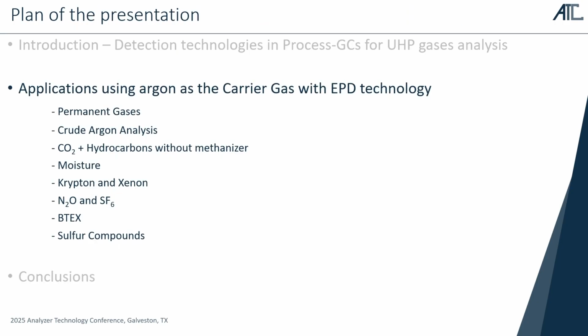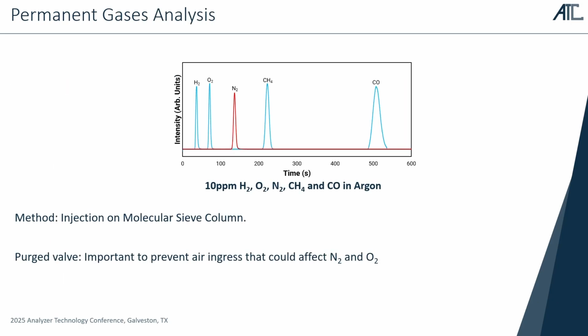So now for some applications that were developed with the EPD technology using argon as the carrier and discharge gas. The first example I would like to present is quite simple. It's actually the measurement of permanent gases in argon. So here you have a standard chromatogram that was acquired for a simple injection on a molecular sieve of 10 ppm permanent gases. But this result highlights the importance of the GC valve that was used, because if the valve is not leak tight, then you would definitely have some interference from air on the nitrogen and oxygen peak. So having a valve that is leak tight is definitely important here.